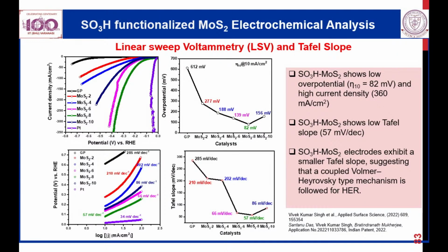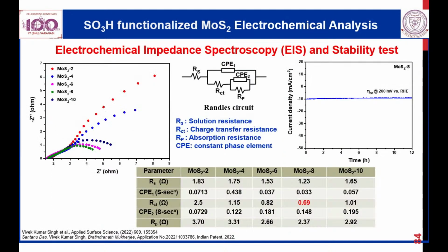Now, looking at the electrochemical data, we see that the hydrogen evolution reaction improves a lot with the sulfonation, up to a certain percentage, and our Tafel slope is 57. You remember just now we discussed 67. Now it's even improved to 57. So we are very close. We are trying to reach 34 like platinum. Some work is still going on in our lab, and hopefully we will succeed soon.